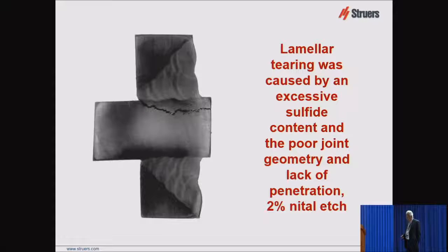Here's another example. And this actually came from a failure of a structure down in Florida. A building was being created, and you can see there's very little penetration here and down here. And this is a typical design problem. And this building had a lot of tears like this. You can see we've got huge weld joints that are multi-pass on each side, but very little penetration here and here. And this is the longitudinal direction.